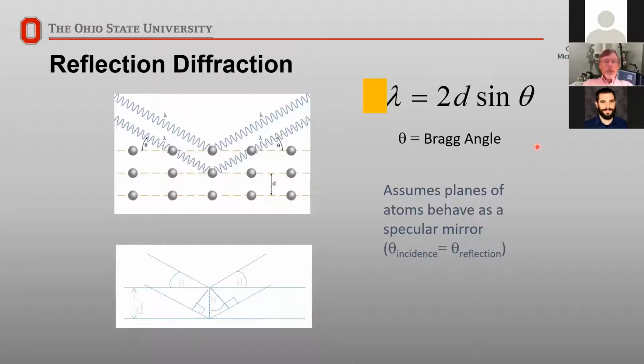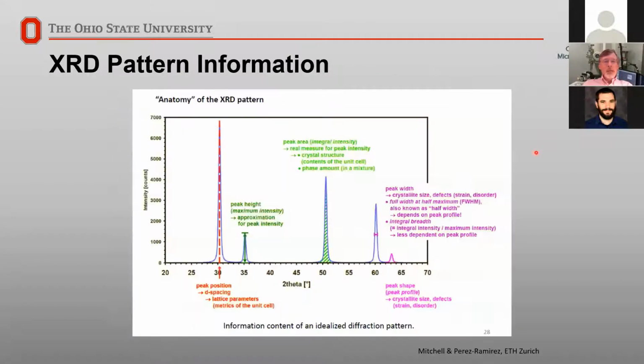So coming out of the machine, we will get something that looks like this, where this is our scattering angle, in 2 theta, and the intensity. So as we scan through the angle, we will see these peaks showing up. Now, the position of the peaks in angle tells us d spacings, but then also we have the intensity, which is the area under the curve. We have the peak width, and actually the shape of the peaks as well. And all those different aspects will give us information about the atomic arrangement.